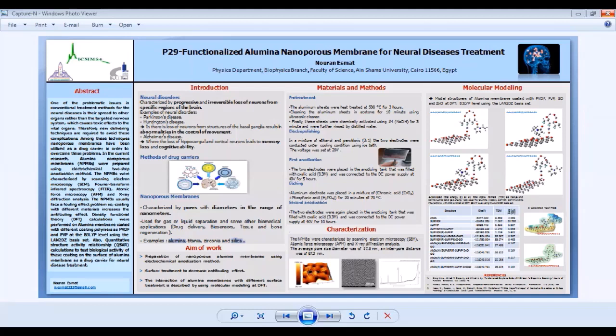Nanoporous alumina membranes were prepared by a two-step electrochemical anodization method. The preparation process is divided into 6 main steps. The first step is the pre-treatment step, in which the aluminium sheets were heated in an oven at 500 degrees and then sonicated in sodium hydroxide and acetone. After that, the electropolishing step, in which the aluminium sheets were electrochemically polished in a mixture of perchloric acid and ethanol to reduce the surface